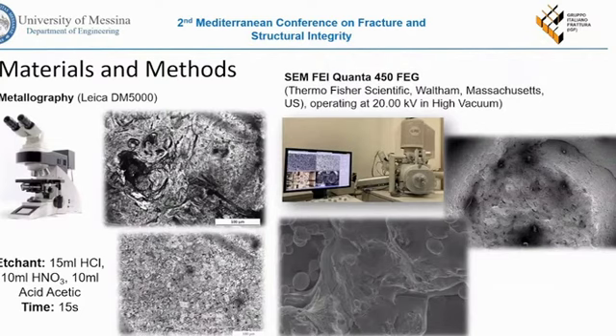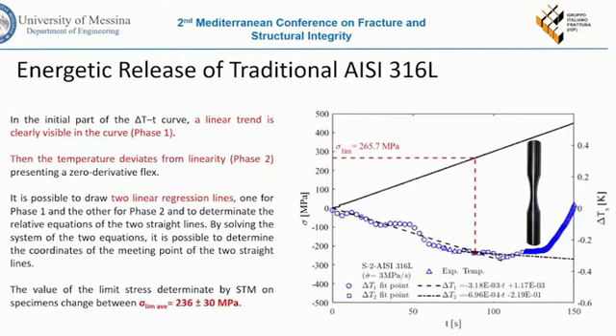We also performed failure analysis, conducting metallographic inspection and SEM inspection. So here I show you the results of this static tensile test. As we can see, we have the linear decrement of the temperature, then the temperature deviates from linearity. So we can make the linear regression of the temperature points of phase 1 and the temperature points of phase 2 and find their intersection. So we can read a value of the limit stress.